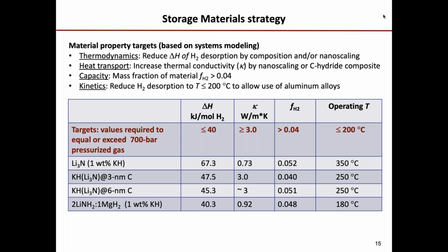So our strategy here in this project is to look at a compositionally tuned version of that, where we substitute some of the lithium with magnesium. And we basically call this a 2-to-1 material. It's 2 moles of a lithium amide and magnesium hydride, and when those react, they turn basically into a mixture of lithium hydride and magnesium amide.